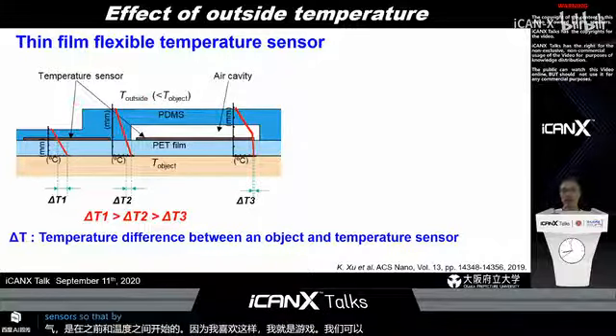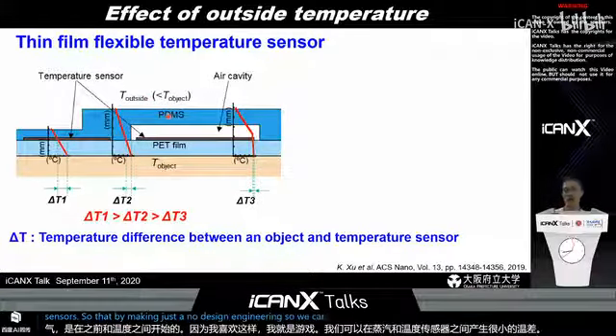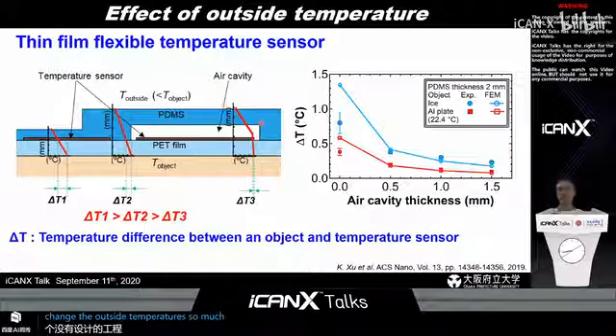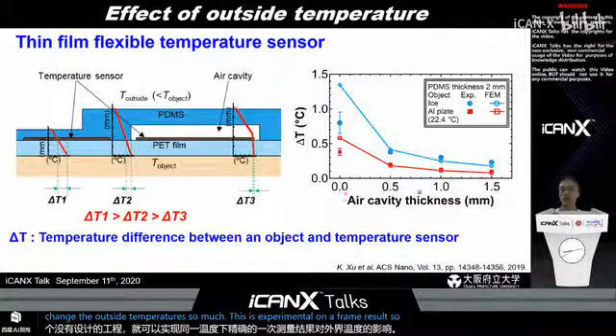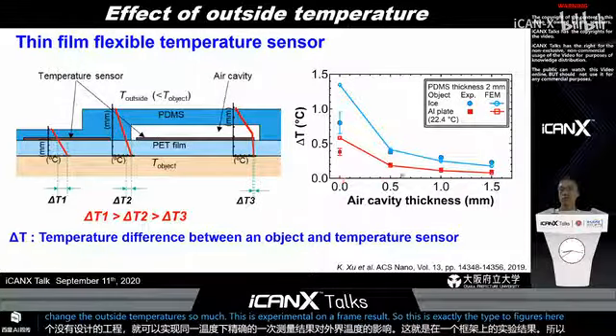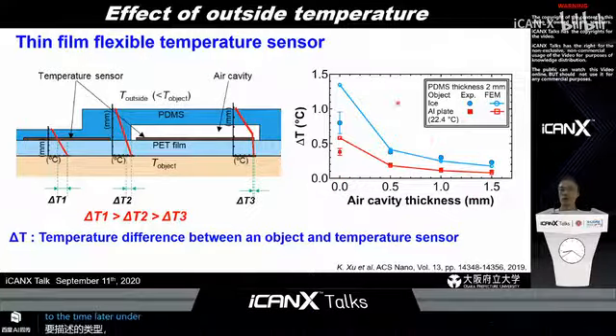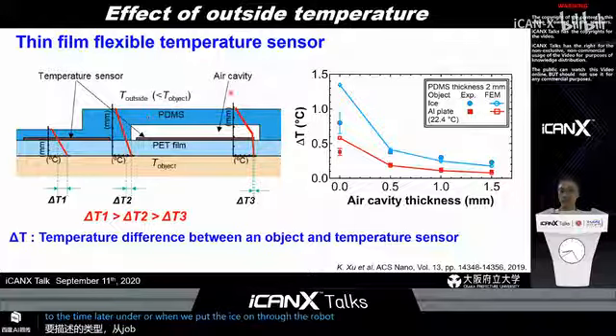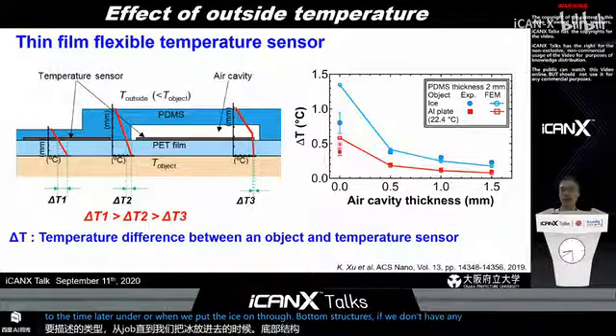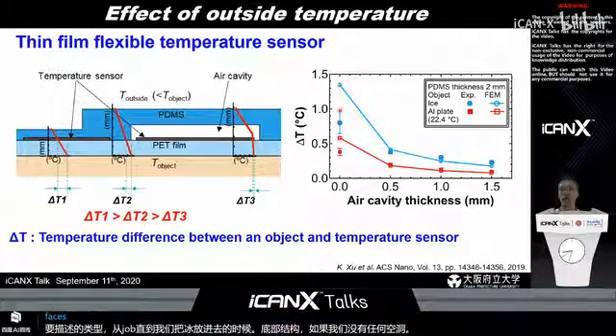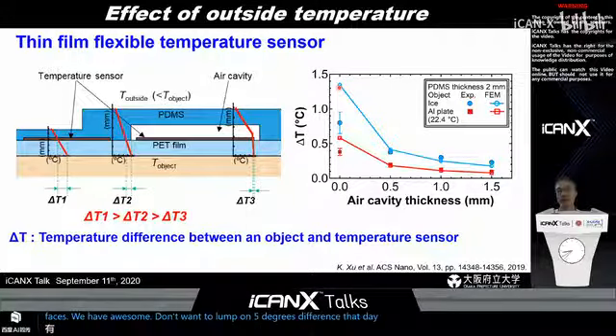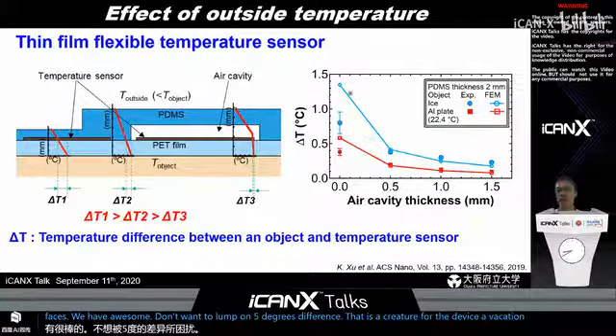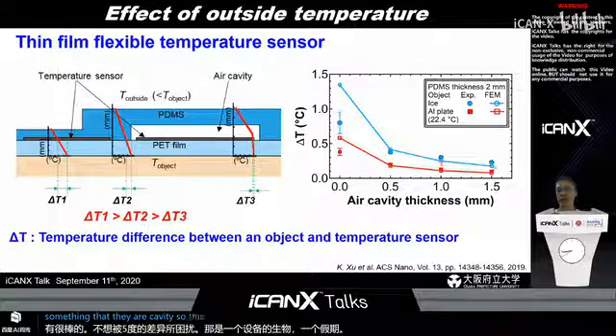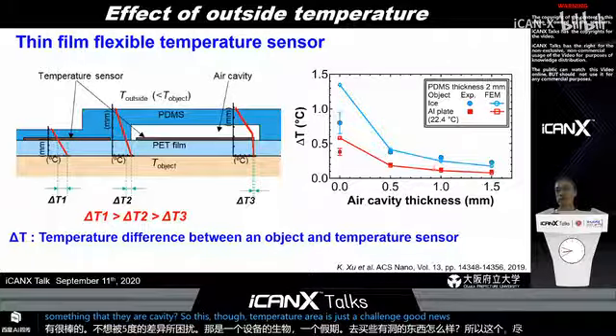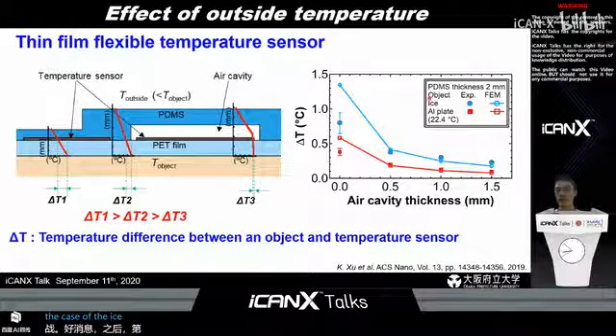So by making this design engineering, we can realize the precise monitoring of the skin temperature without affecting the outside temperatures so much. And this is the experimental and FEM result. The x-axis is the air cavity thickness here from 0 to 1.5 millimeter. And then, when we put the ice over these structures, if we don't have any air cavity, roughly 0 degrees C ice cases, we have some 1 to 1.5 degrees difference. That is critical for the wearable device application. However, by inserting the air cavity, this temperature error is drastically reduced up to 0.2 degrees C in the case of the ice, roughly 0 degrees C on top.